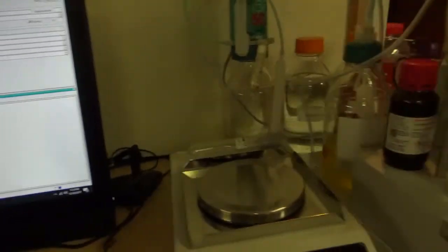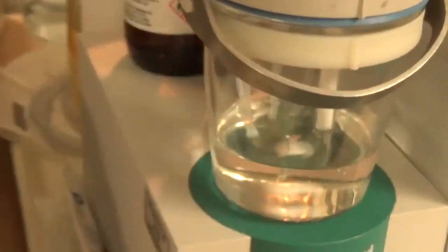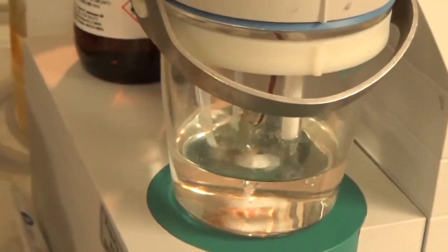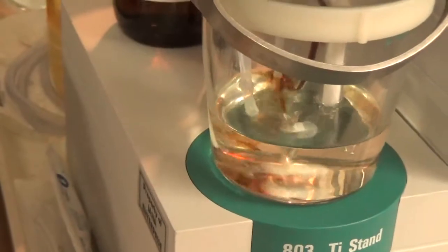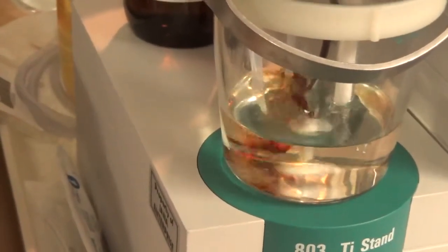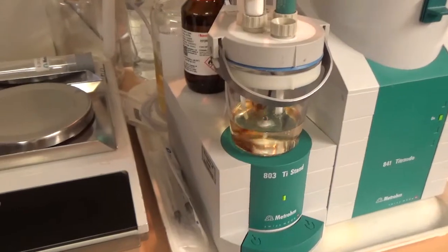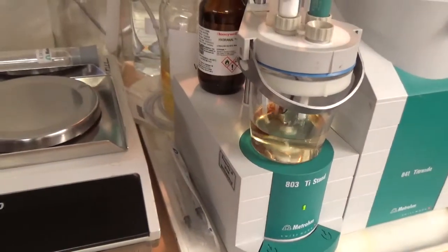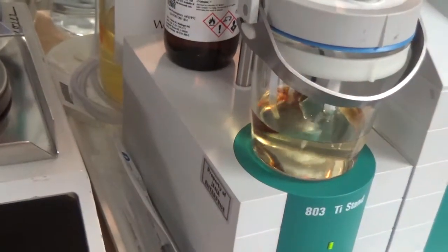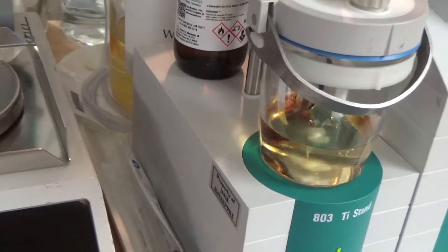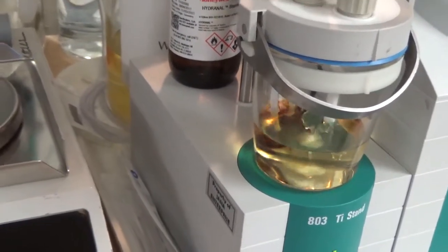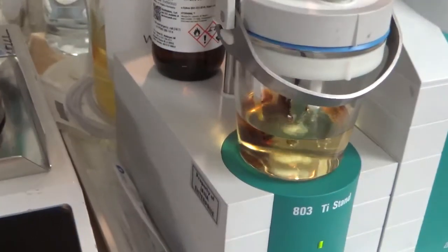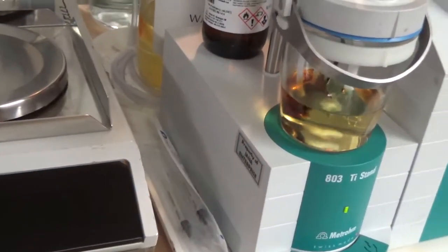To do that, we start the run. The stirrer starts. So when there is moisture, the liquid will be clear. Clear means there is moisture present. So once this iodine solution, the Karl Fischer reagent, is added, the liquid will turn to pale yellow to dark brown, in that color range when there is no moisture. Once you add a sample with moisture, the color becomes clear, and then the titration continues until the moisture is consumed by iodine and the color changes to dark brown, from yellow to brown.